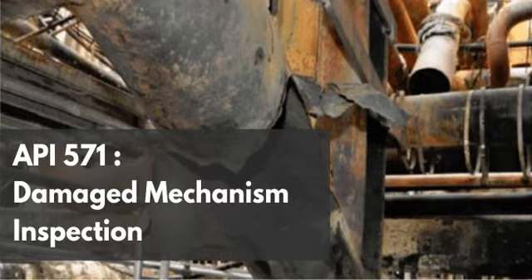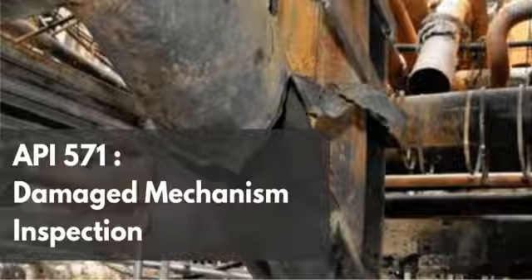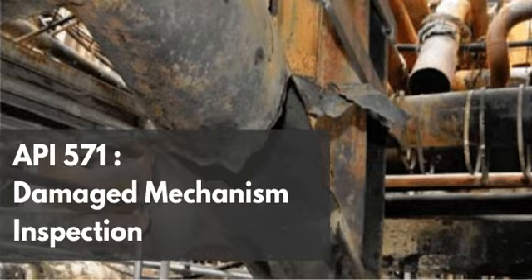Okay, but just to be clear, if I see chromium on that mill cert for standard carbon steel, that doesn't mean it's suddenly corrosion resistant. Exactly. No, not at all. These are trace amounts, often fractions of a percent. They are not intentional, high percentage alloying additions designed to radically upgrade the chemical resistance of the base iron. Right. They might help the steel mill roll the plate better, but they won't stop degraded MEA from eating the pipe. Okay, so that is carbon steel, the baseline, the workhorse of the refinery.